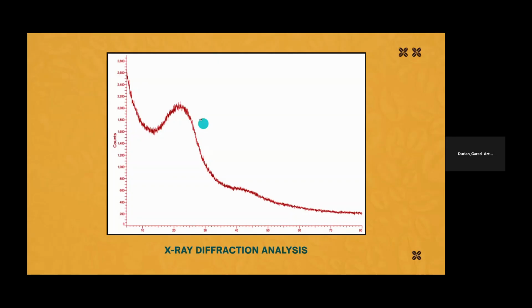Moreover, the gradual decrease in XRD peak intensity at higher 2 theta angles reflects diminished scattering from ordered crystal planes, which is consistent with the sheet-like structure of graphene oxide. The lack of long-range crystallinity supports the amorphous nature seen in the TEM observations. Additionally, the small hump observed around 10 to 12 degrees at 2 theta represents the interlayer spacing of stacked graphene oxide sheets. The broad nature of this peak suggests that the layers within the GOQDs are exfoliated or highly disordered, further confirming their fragmented structure.